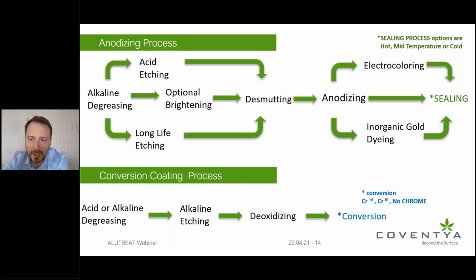In order to apply a successful powder coating operation, you have to have first an intermediate conversion coating on the surface that would reduce corrosion, but also increase the adhesion. There are several ways to do it, starting from acidic cycle to alkaline cycle, ending with conversion coatings, starting with classical Chrome 6, which are currently on the way out due to their hazardous nature. We are also providing Chrome 3 solutions for our customers according to their needs.